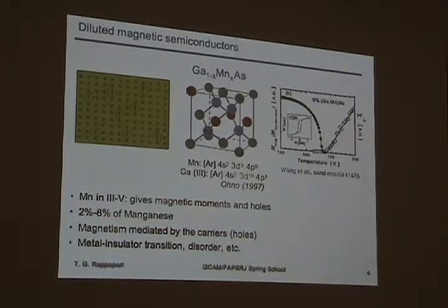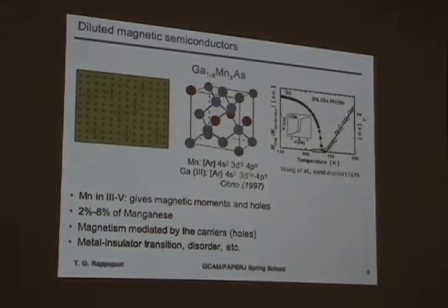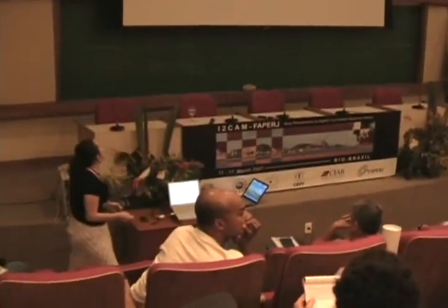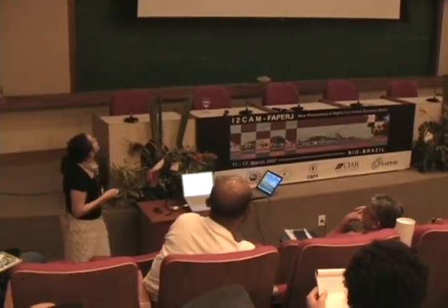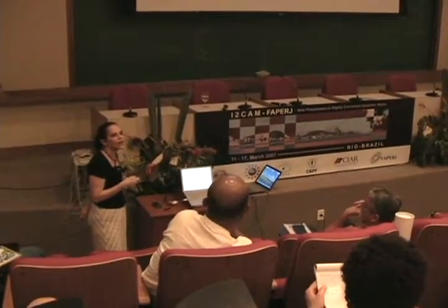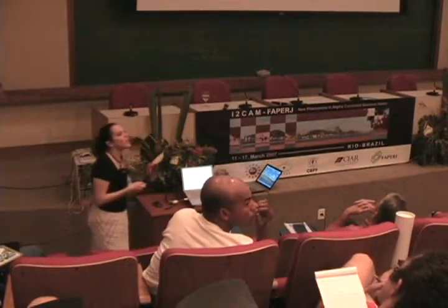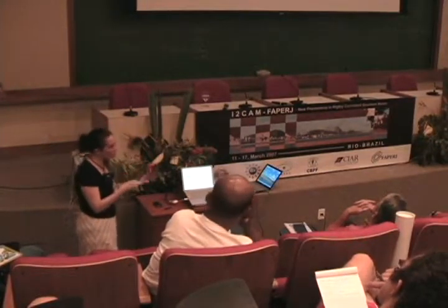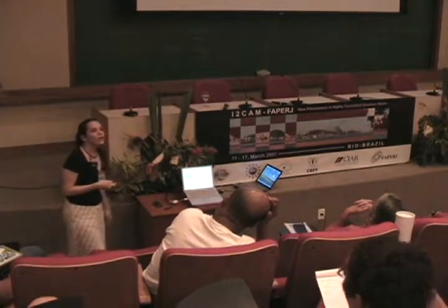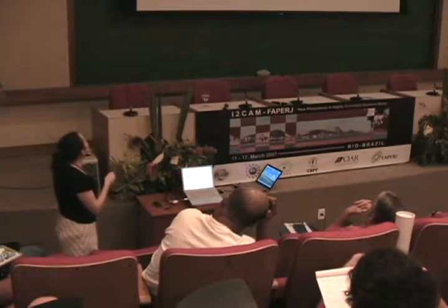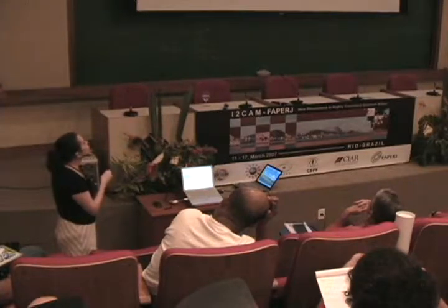Do you know the separation of the moment? The separation of the magnetization. Oh, it's less than, okay, for manganese it's 5/2, but it's a little bit less. But it's kind of complicated to calculate this, because when you incorporate this manganese, many of these manganese are not really incorporated, substituting gallium.